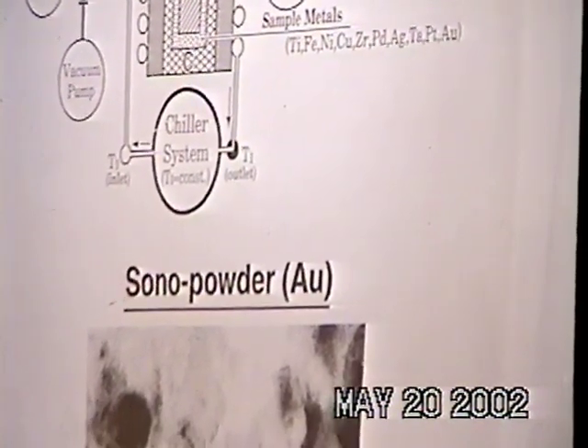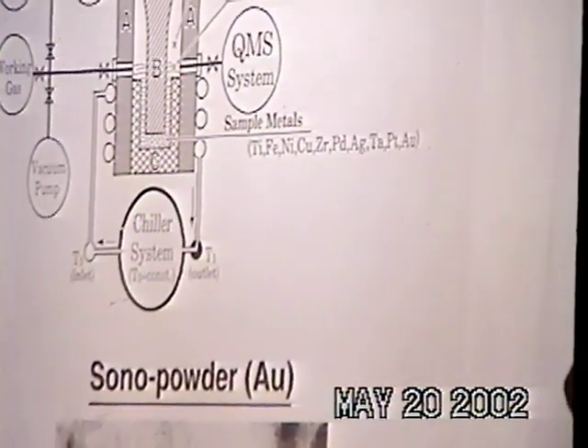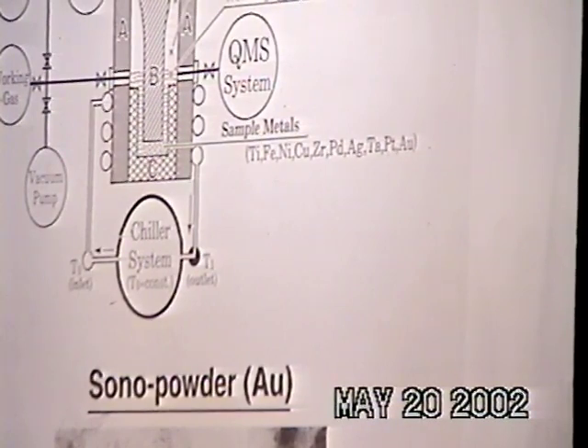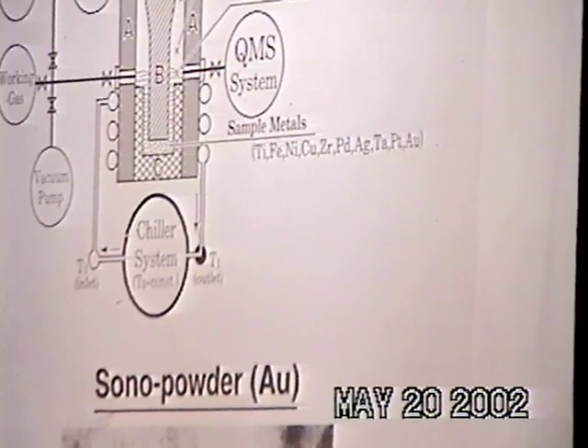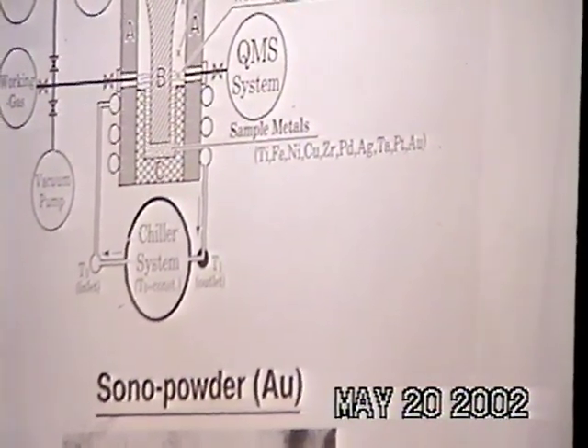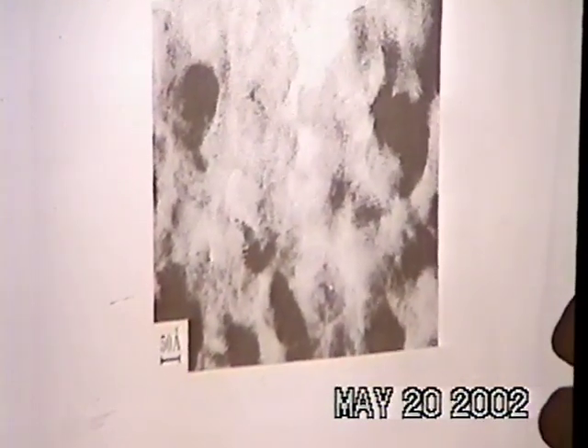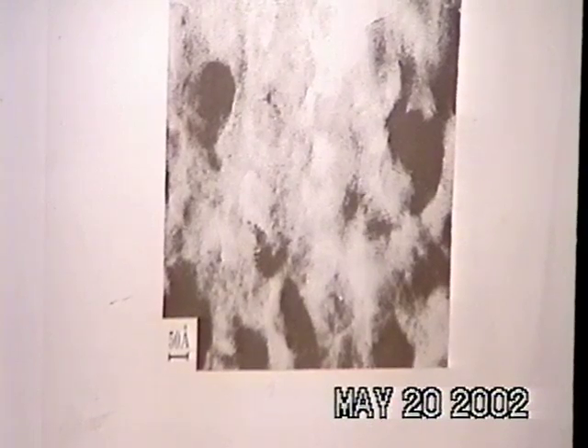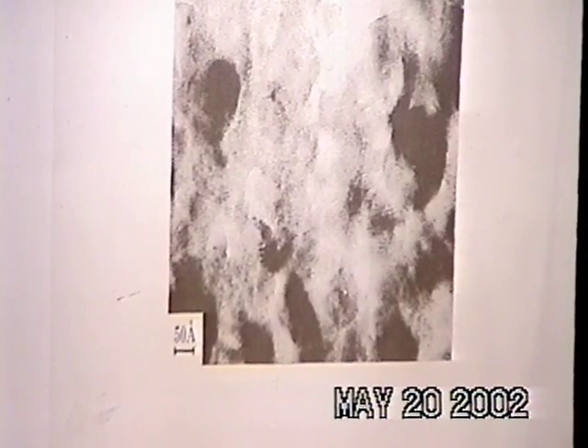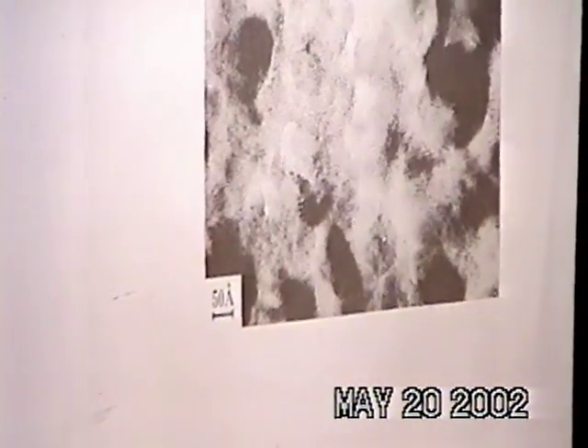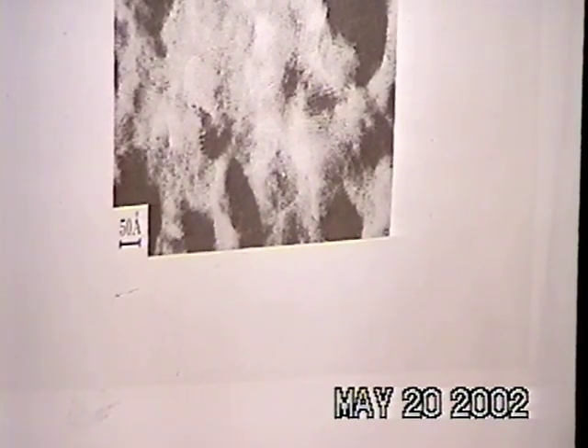Sonic power of 300 watts with 19 kilohertz during about 1 to 2 days was supplied to metal coils immersed inside the working liquid. As a result, the metal changed into an ultrafine powder of nanometer scale, called simply sono powder. The lower side electron micrograph shows gold sono powders as a typical example. Gold has been considered a very stable metal against chemical attack, but its color changed into black because of their size of 50 to 100 angstrom, nanoscale.